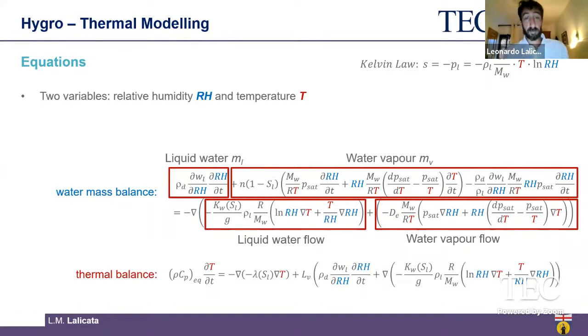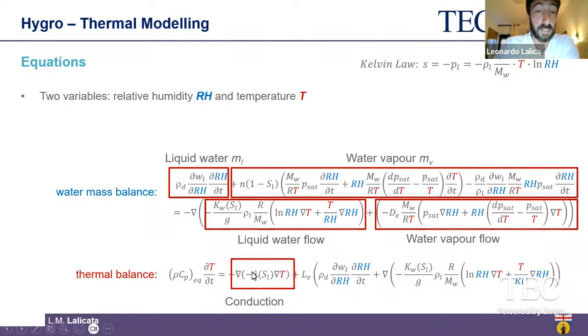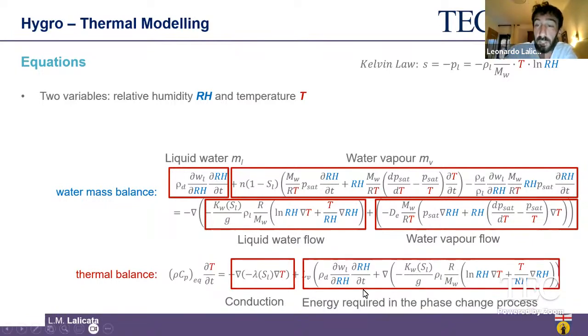In terms of thermal balance, the equation obviously has the same shape, but here the storage term in this case is a function of the heat capacity of materials, but the flow is given by the conduction that is described by the Fourier's law, and there is also another term which is often neglected but is very important in our case, because this is the energy required in the phase change process that obviously is a function of the latent heat of evaporation of the water.